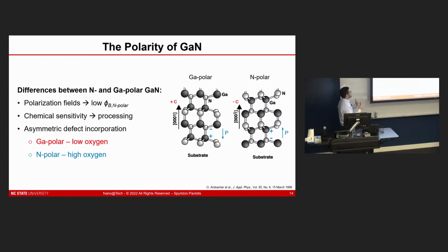They're essentially the same material, but they actually have some different properties, which almost you can treat them as different materials in a way. From an electrical engineering perspective, in some ways they almost behave like very different materials. Because of the difference in the direction of the polarization fields, when you make a contact in nitrogen polar GaN, you have a different barrier height, so a different Schottky barrier height and a different turn-on voltage for your diode. And so that brings in hints that we have to think about how to engineer that interface.